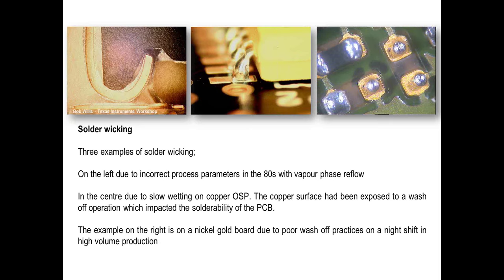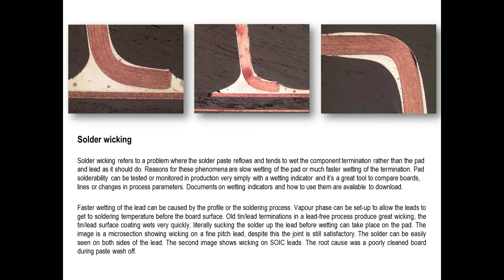On the third example, on the right-hand side, you can see a similar phenomenon where the solder paste has just reflowed and balled on the pad surface. The reason for this was wash-offs: washing off a board, but engineers not looking at the compatibility of the board finish and the wash-off process being used. So the key thing is that you want to minimize wash-offs wherever possible by setting good solder paste printing criteria, but if you have to do it, make sure you do it properly and make sure you don't affect solderability or wettability. Solder wicking can also take a great volume of solder away from the pad surface, which is not a good thing because the amount of solder will affect the reliability of the interconnection.